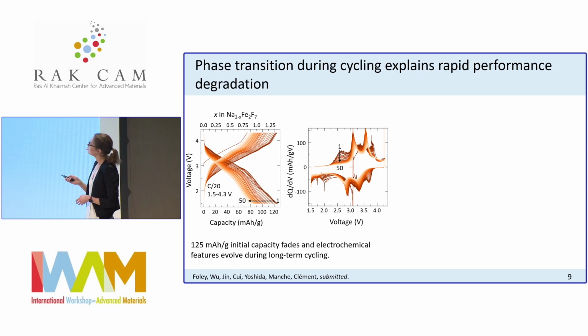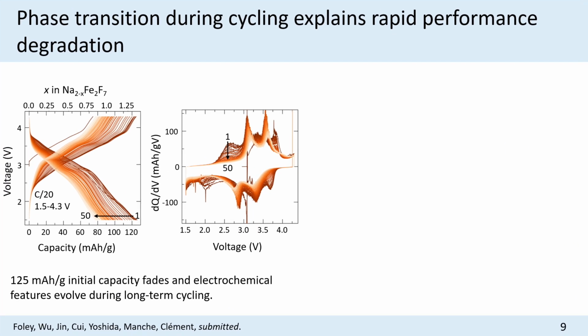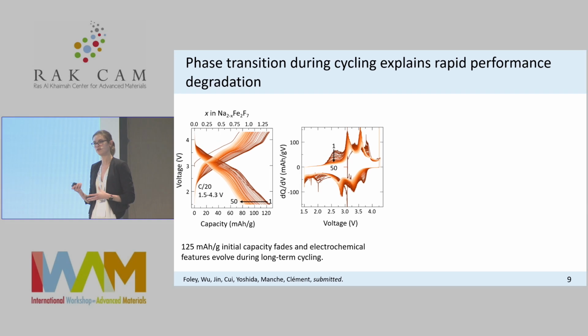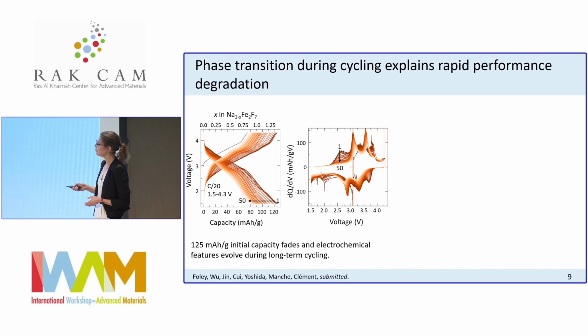If you look at the electrochemical properties of this material, this is the typical voltage curve that we show for battery materials when we test them. The important number here is what we get on discharge. On the first discharge, we get about 125 milliamp hour per gram of capacity, which is okay for a sodium-ion cathode. But the problem is the degradation of the performance during the first 50 cycles. At cycle 50, we are at less than 80 milliamp hour per gram. So there's clearly degradation happening in the material.